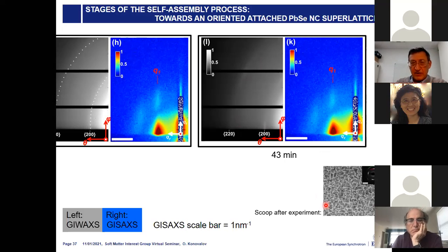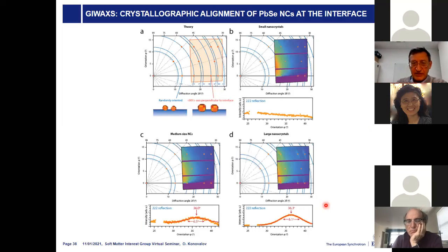And after the experiment, we also take the samples for characterization. So now, from this image, you can see that if we had the nanoparticles on the surface oriented randomly, in all types of orientation, we would have circles. But if, for example, one face, like for these crystals the 100 face, is oriented upwards, then we should see the Bragg peaks. And this also presents how we calculate where to put a detector to follow the process. So then this is already experimental results.